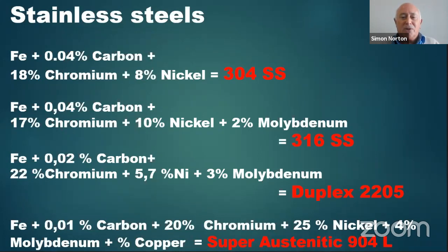Just to give you some idea of the common stainless steels which you might come across and their compositions: 304 stainless steel, obviously containing iron, a small percentage of carbon, and then 18% chromium, 8% nickel. 316 stainless steel contains a percentage of carbon, 17% chromium, typically, and these are typical values, 10% nickel, and 2% molybdenum. Now, we're talking here about 316. If we were talking about 316L, we would mean the low carbon 316. Many people that I've come across implement 316 but forget that they must order the 316L, which is low in carbon and therefore of value when you're welding stainless steel.